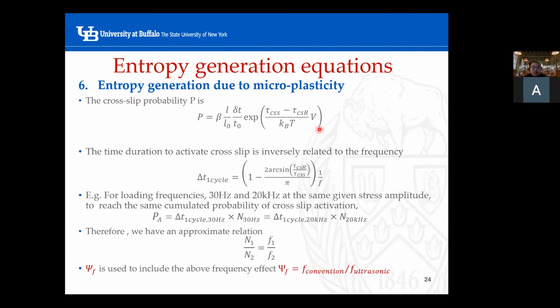I find that there's actually a cross-slip probability for the cross-slip of screw dislocations. It is related to a coefficient: the relative length, the duration of time versus the reference time, the resolved shear stress minus the critical shear stress that can activate the cross-slip, over the Boltzmann constant, absolute temperature, and the volume of the screw dislocation.